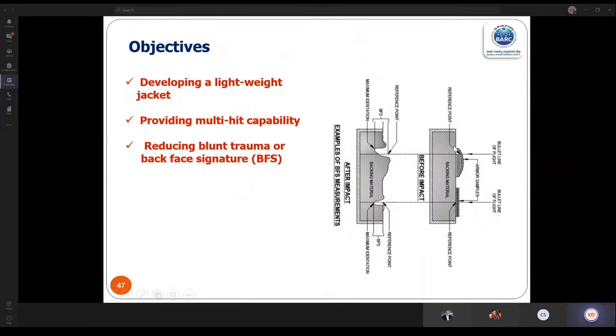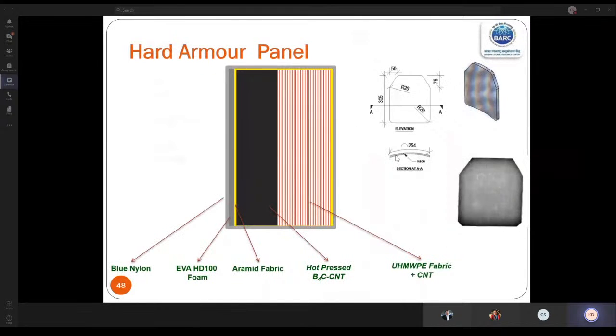How do we measure it? Typically there is a plasticine kind of material which resembles our body muscle, and on top of that we put our armor panel, and the bullet is fired, and then we measure the depth into the plasticine. This gives an impression, so we measure the depth, and that is called blunt trauma or backface signature. This should be below a certain value in order to save our soldiers. For the hard armor panel, there are two components we have used: hot pressed boron carbide and carbon nanotube composites, and then a laminar structure of ultra high molecular polyethylene and carbon nanotube.